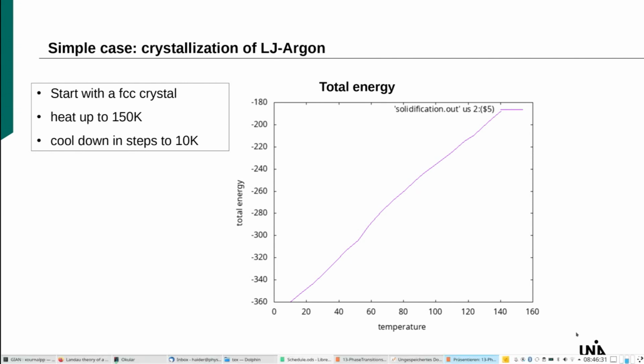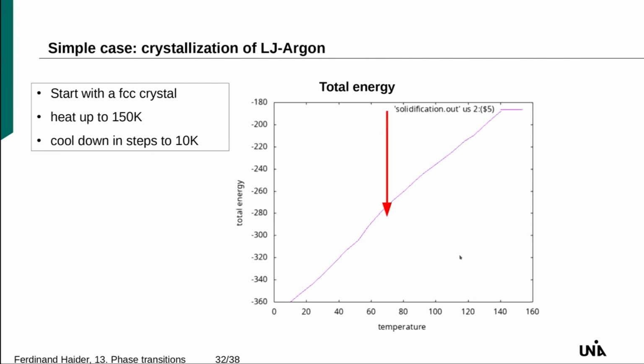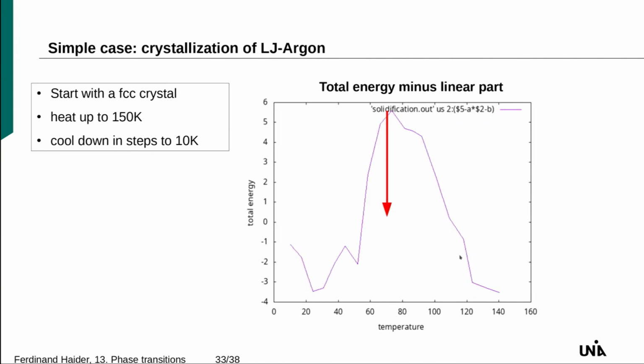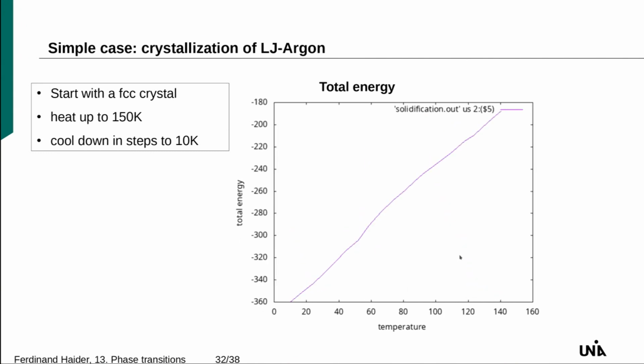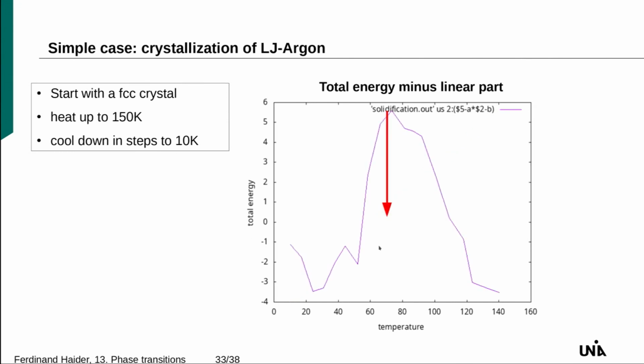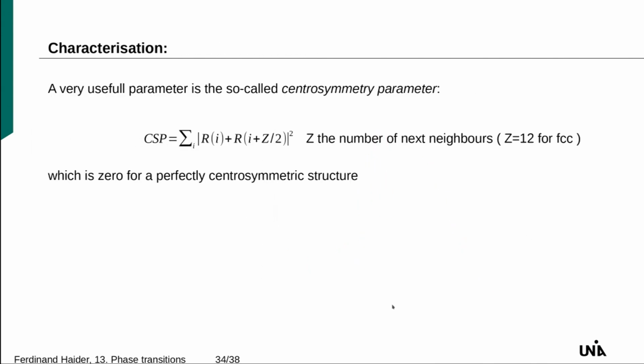Here is a function of temperature, the total energy, and if you look closer, if you take the derivative of this curve - this is just from an MD simulation - you find this maximum here, where the solidification starts, or the melting, going in the other direction, starts.